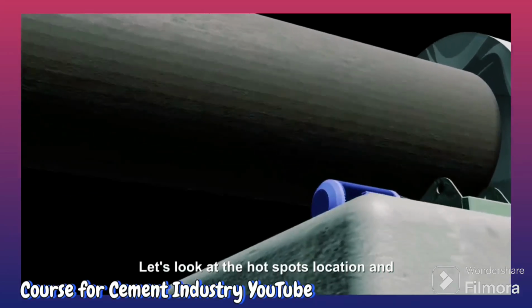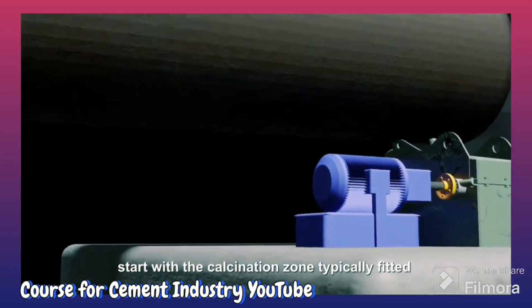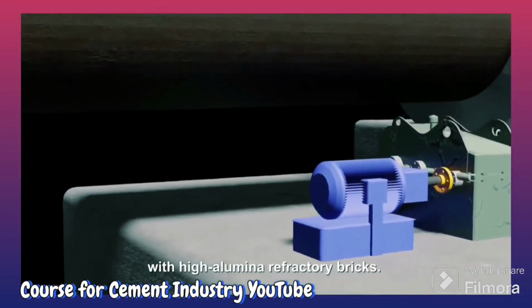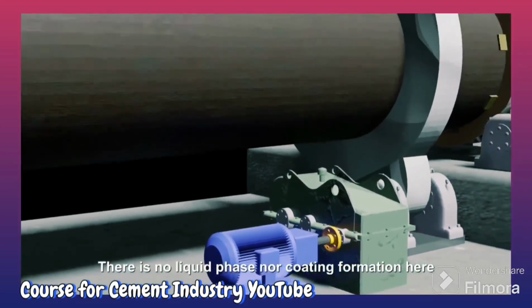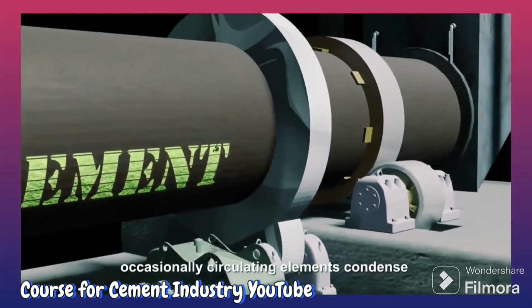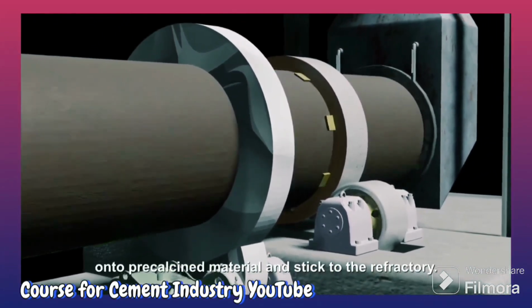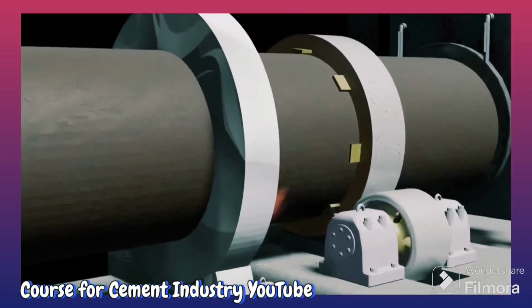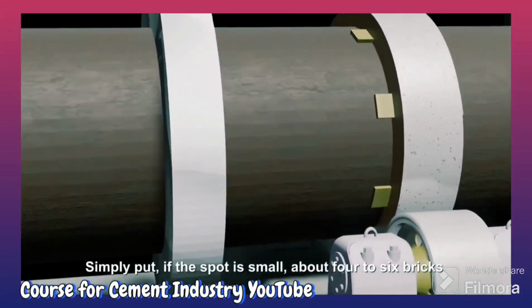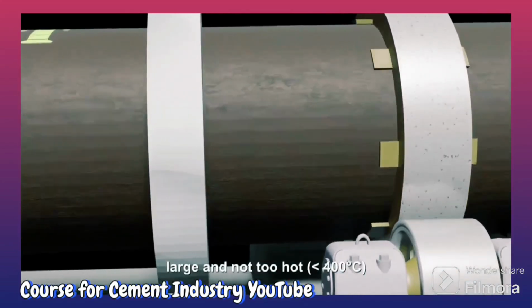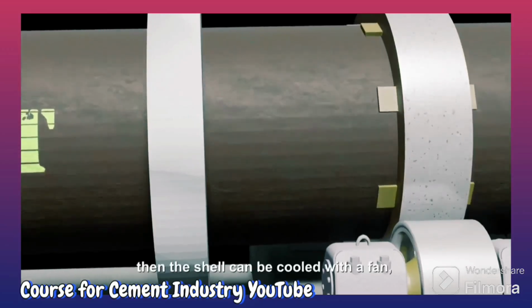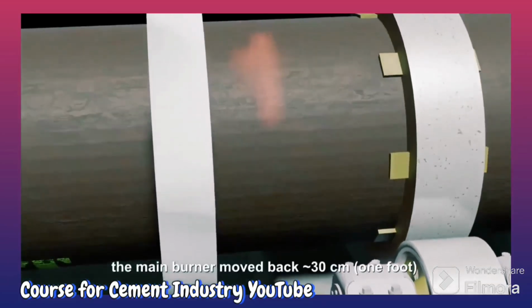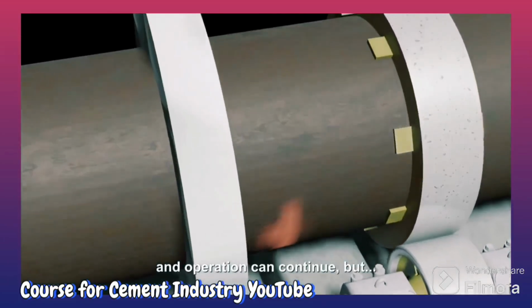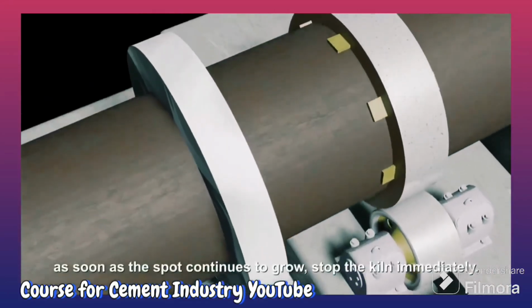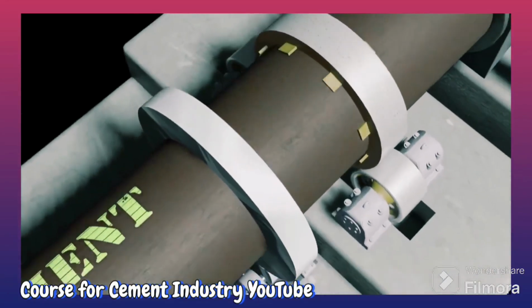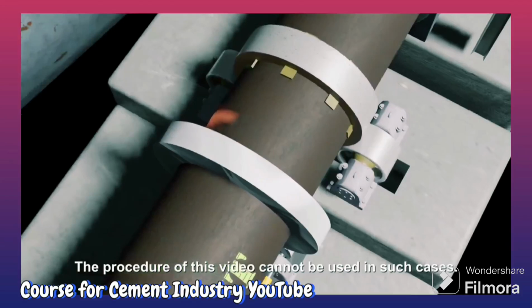Let's look at the hotspot locations and start with the calcination zone, typically fitted with high alumina refractory bricks. There is no liquid phase nor coating formation here. Occasionally, circulating elements condense onto precalcined material and stick to the refractory. Simply put, if the spot is small, about 4 to 6 bricks large, and not too hot, under 400 Celsius, then the shell can be cooled down with a fan, the main burner moved back 30 centimeters, and operation can continue. But as soon as the spot continues to grow, stop the kiln immediately. The procedure of this video cannot be used in such cases.